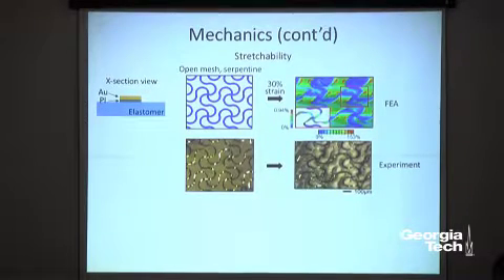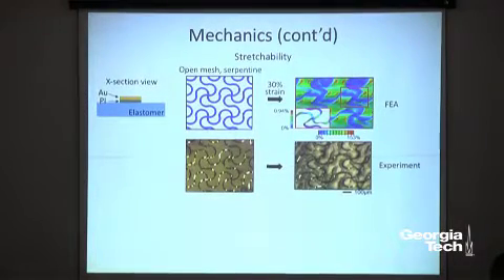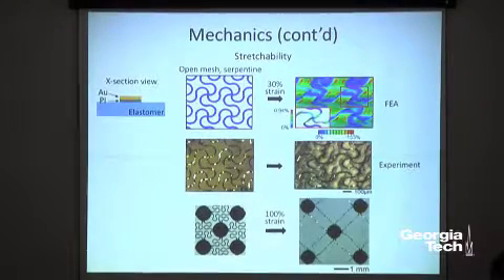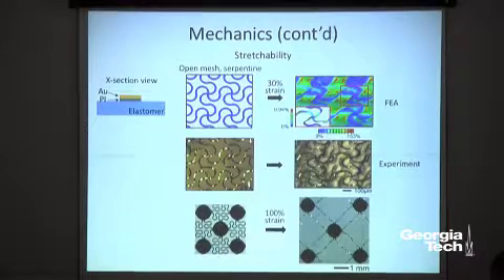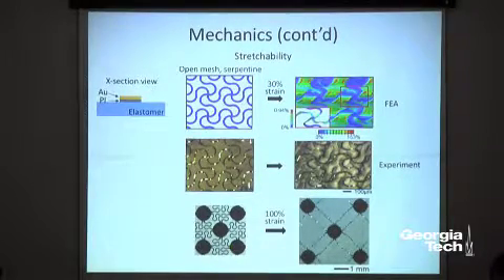Right? Why 30%? It's based on our targeted skin. Our skin has a maximum stretchability of 30%. After that, it's going to have tissue damage. But if you look at areas like the elbow or joints, it can be even higher than 30%. So if you look at those areas, then you can modify your design. So instead of that, now we call it island bridge. So you have these islands, and there's a bridge interconnect based on these serpentine structures. Now this guy can be stretched up to 100% or even higher. So depending on your applications or targeted locations, you can tailor your design so that you can have maximum stretchability without fracturing your electrode or electronics.